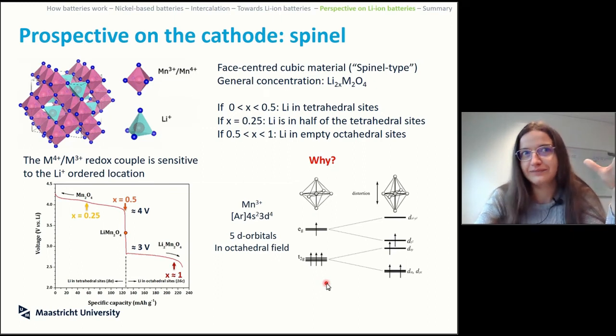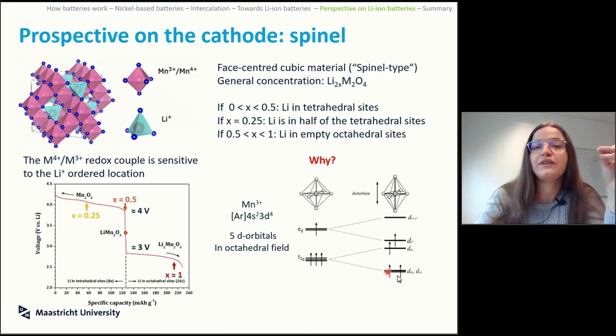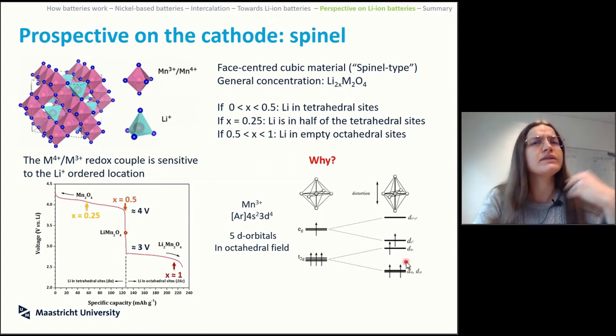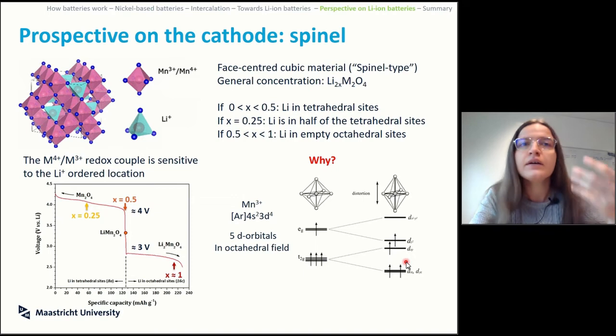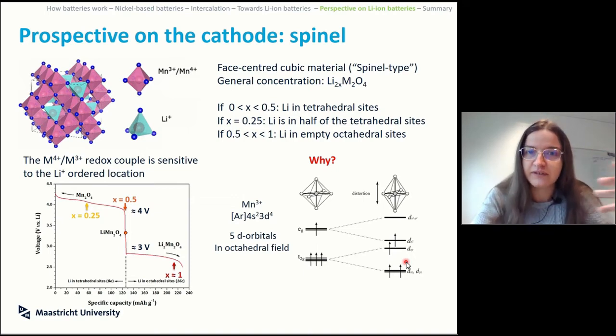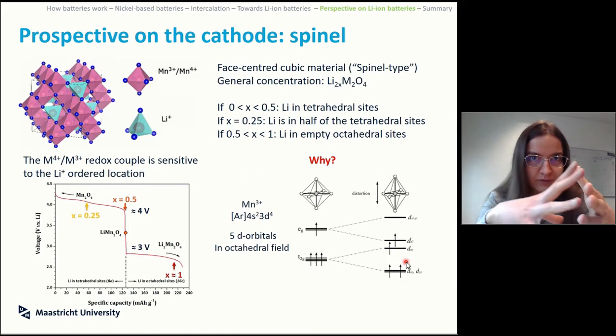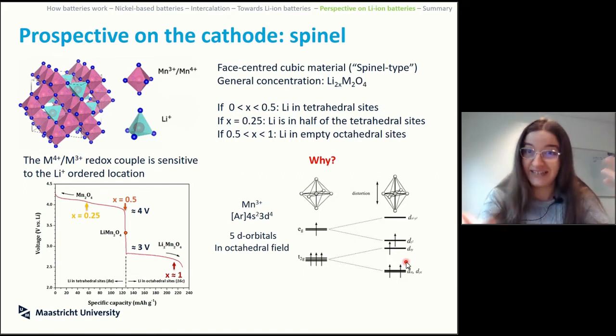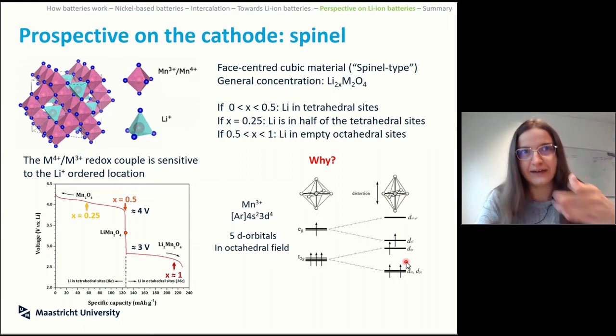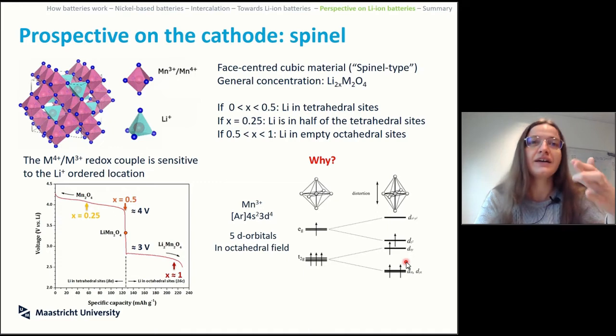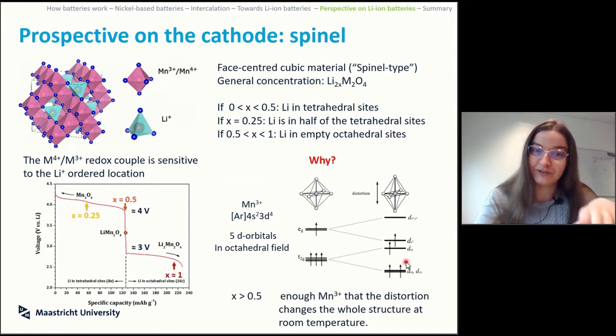So it's not that it can't stay like this, but not necessarily, because there could be a point in which it's beneficial for the structure to try and remove this redundancy in energy. Why are all these orbitals at the same energy and all equally feeling the same coordination if we could do something different? The something different here relates to changing the coordination environment. So you have bond elongation, bond compression. This is called Jahn-Teller distortion. It's a thing in molecular chemistry that some of you might have encountered. In solid state chemistry, Jahn-Teller distortion is still a thing. So with enough manganese 3 plus, you have a full distortion of the whole business.